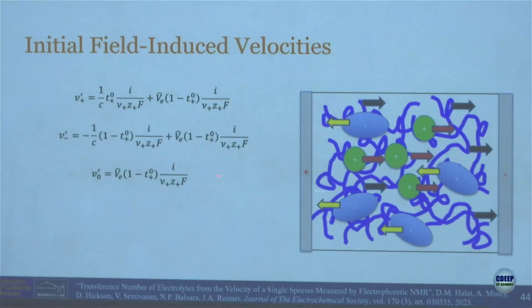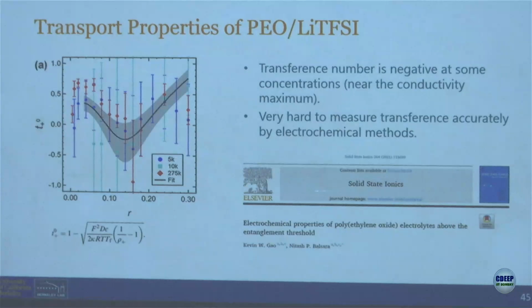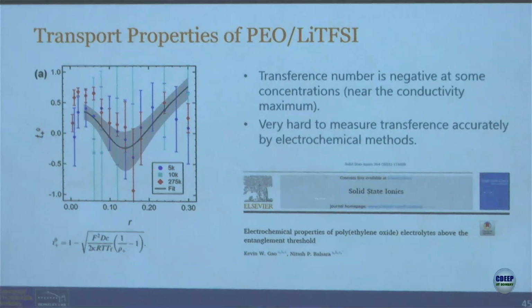This particular expression I was very proud of when I saw it, because it's not there in the literature. It has been assumed to be 0, and it's far from 0, except if t plus 0 is 1, and that's a pathological case. So we set about measuring this parameter called t plus 0 in our polymer electrolyte. The classical way of measuring it is this formula. You have to measure a diffusion coefficient, a current fraction, the activity coefficient, and the conductivity. By the time you make all these measurements and you're honest, you will get error bars that look terrible.